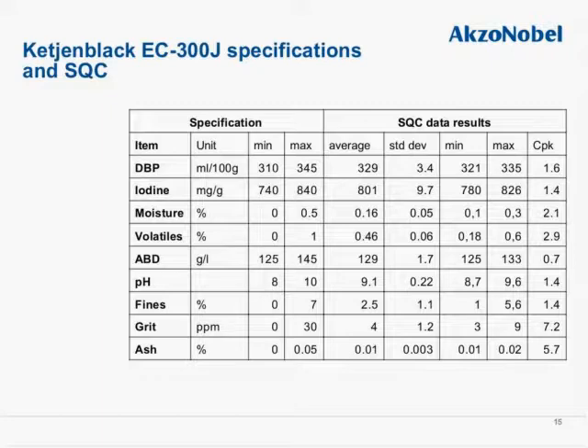Grits are extremely low. Ash is 0.05% being maximum. On average, actually, it is 0.01. The last column indicates the CPK, and as you can tell, the value is very high. So that means it's a very tight control process. Ash is very small, which makes both these products suitable for applications where purity of the carbon black is very important. Applications such as electronics and high voltage wire and cable are highly sought after, and they actually benefit from using Ketjenblack product.